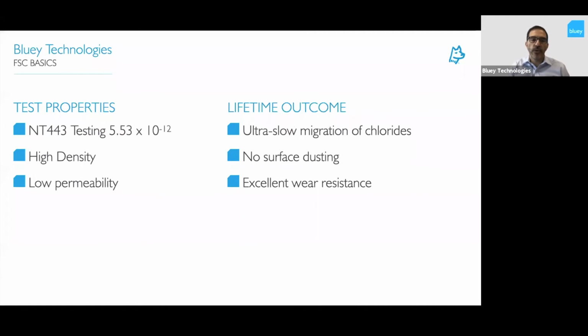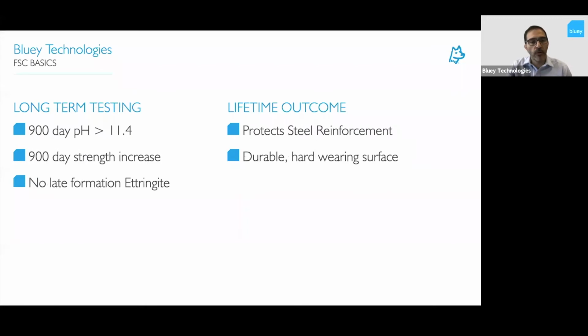We also complete NT443 testing, and we know that we have a very slow migration of chlorides through this type of cement system. We know that it's very high density, and we know it's low in permeability. So we also have no surface dusting and excellent wear resistance. So again, all lifetime properties that we know will lead to a longer life outcome.